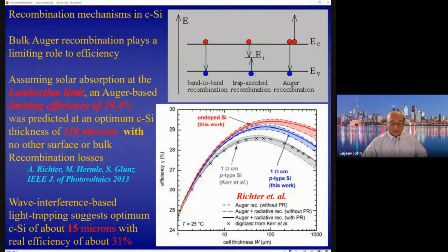A second important effect is due to defects inside the structure, say dangling bonds or dopants, which create defect states inside the gap. So the electron and the hole can get trapped at these defects and then recombine non-radiatively, giving off thermal energy, and that energy is lost. And the third is an intrinsic effect due to the Coulomb force between electrons, so that an electron that's excited here can fall down to the valence band, but instead of emitting light, the energy can go into exciting another electron in the conduction band to a higher energy, and that then relaxes back by thermalization back to the top of the conduction band, and this is referred to as Auger recombination.